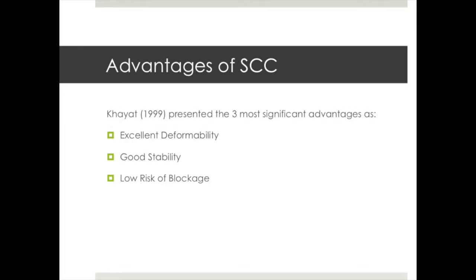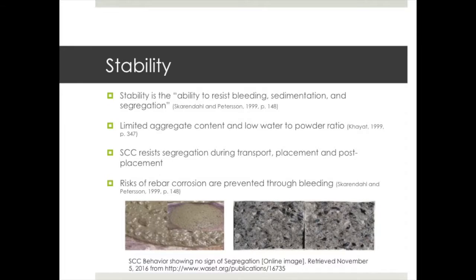Khayat presented in his recent journal article that the three most significant advantages of self-consolidating concrete are excellent deformability, good stability, and low risk of blockage. Stability is defined as the ability to resist bleeding, sedimentation, and segregation, which are both possible due to SCC's limited aggregate content and low water-to-powder ratio. Because SCC resists segregation during transport, placement, and post-placement, the risks of rebar corrosion from the upward migration of water, known as bleeding, are prevented. As seen in the figure, there is no segregation of the aggregates.